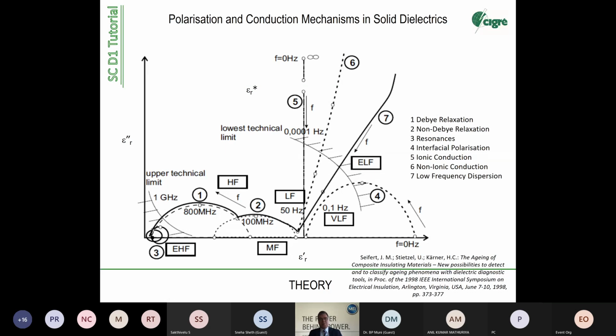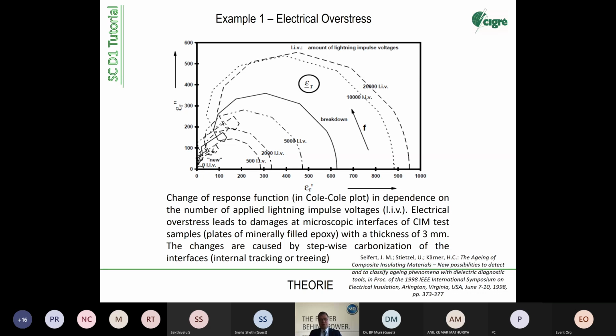I start with an example. What you can see of a material that is aged or stressed. Here, on the very left bottom, you see a new material. You see a Cole-Cole plot of the material. It's difficult to see. It's a very small dielectric response. And now we apply, this is a kind of quartz powder filled epoxy applied in auto insulation or in transformers. Now we overstress the material. So we apply lightning impulse voltages, 500 impulses, 2000, 5000. Here sometimes we see breakdown, at this point. But some materials also resisted more than 10,000 impulse voltages.